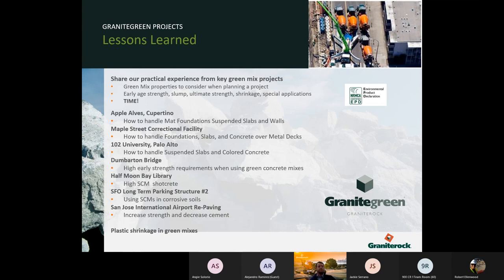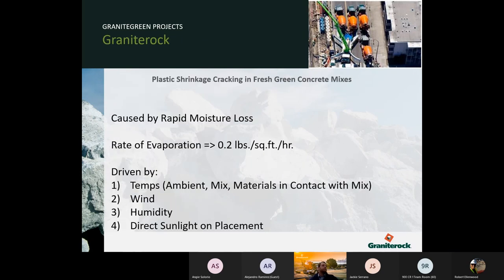One key thing to think about is that because these mixes aren't going to set up as quick, it is left to the ambient environment. So a concern is plastic shrinkage cracking. If you're not familiar with placing green concrete, you might actually trap the bleed water before it's ready. It takes a lot longer to set, meaning the bleed water comes later, and this can have a bad effect on the concrete. This is plastic shrinkage cracking. It's caused by rapid moisture loss driven by wind, temperature, humidity, and direct sunlight.